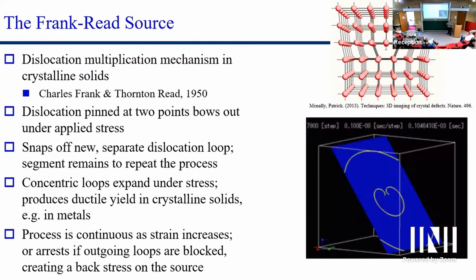When you've exhausted all your sources, then as you keep pushing the strain, the stress rises, and eventually the largest crack becomes unstable and you can get fracture. Okay, but the other thing is, while dislocations are moving, they might pin in two spots and make a new source. Dislocations can also pin by a variety of mechanisms. They can tangle on another dislocation. They can just cross-slip funny and stick themselves in the lattice. They can be attracted to a vacancy. There's all kinds of ways dislocations can pin.